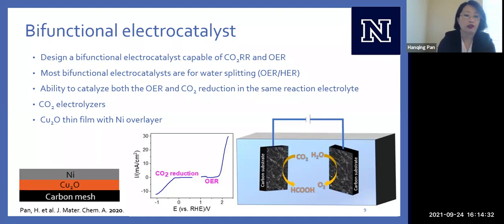And so most bifunctional catalysts that are currently out there are for water splitting. So for water splitting on the anode side, we're making oxygen, so oxygen evolution reaction, and on the cathode, we're generating hydrogen. Instead of hydrogen evolution reaction, we want to couple oxygen evolution reaction with our CO2 reduction reaction. And if we can couple those 2 together, we can start to think about making CO2 electrolyzers. And because there is no good CO2 reduction catalyst out there, there's very few CO2 electrolyzers that are currently being commercialized.